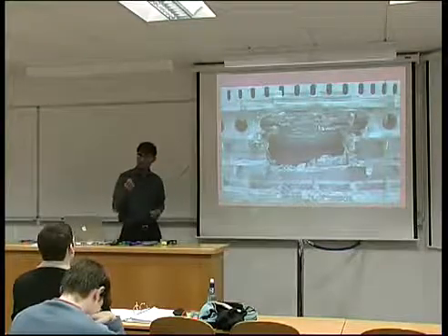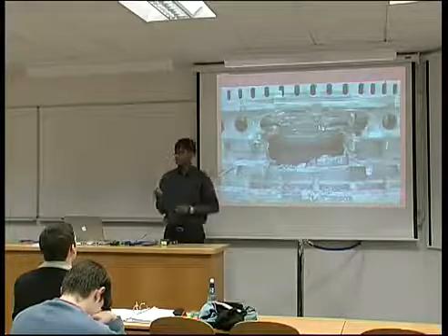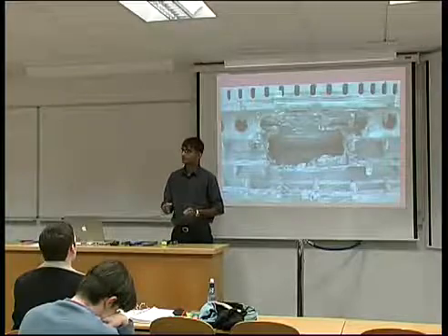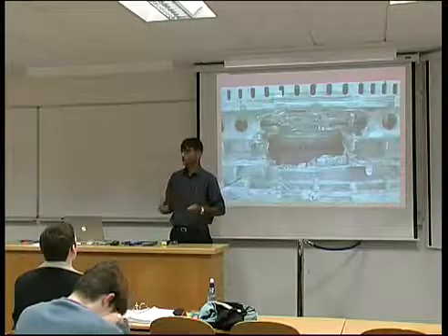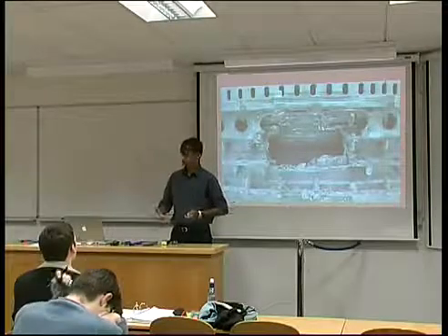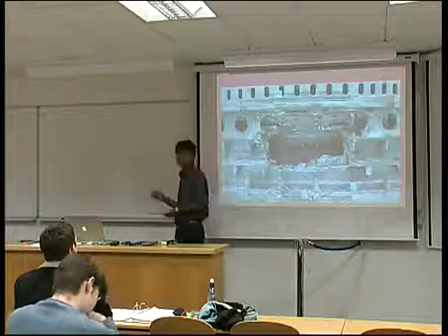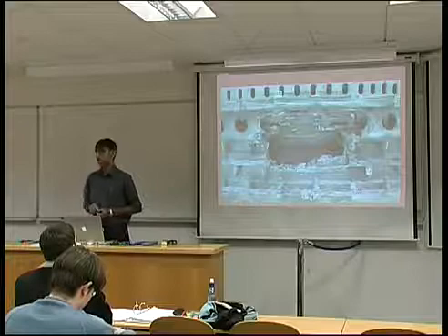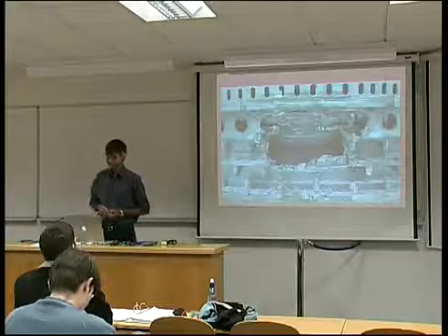Yeah. So it's got a protective oxide film, which is like aluminium. And like aluminium, it has a very, very large enthalpy change when you oxidize it. So once you get the reaction started, and that's the critical thing, it's very hard to stop it. Okay?